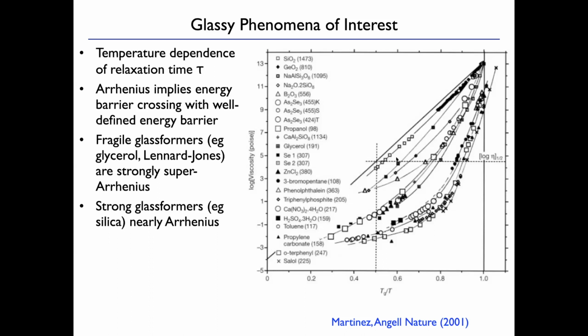And you can see that different glassy systems have very different shapes of this curve. So some of them are pretty straight. Those are called strong glass formers. And those are network glasses like silica, okay? Like what makes our windows or the vases that I showed you earlier. Then there are fragile glass formers, okay, where the relaxation time rises much more rapidly than you would expect based on the Arrhenius rule, okay? Lennard-Jones is an example of that, but glycerol, lots of liquids are strongly super-Arrhenius, so this is called super-Arrhenius. It's faster than Arrhenius as you lower the temperature.